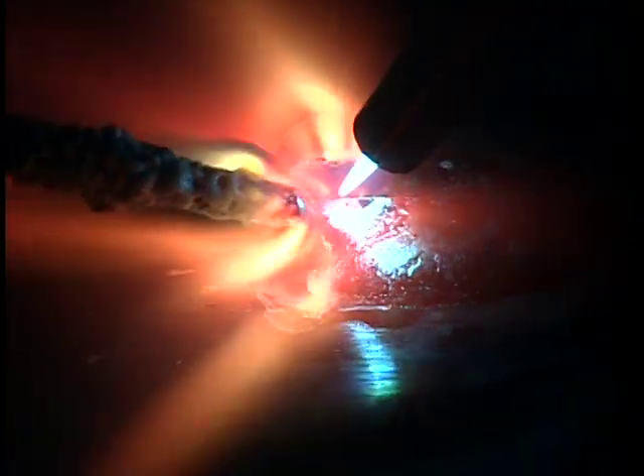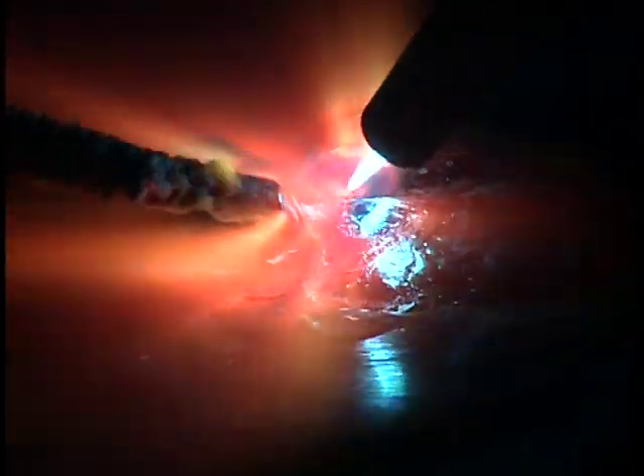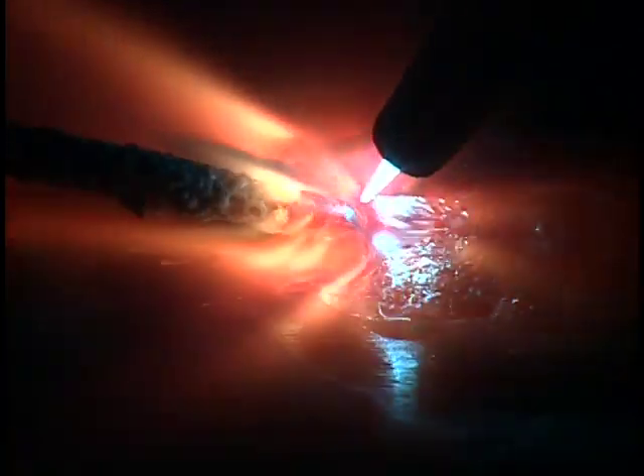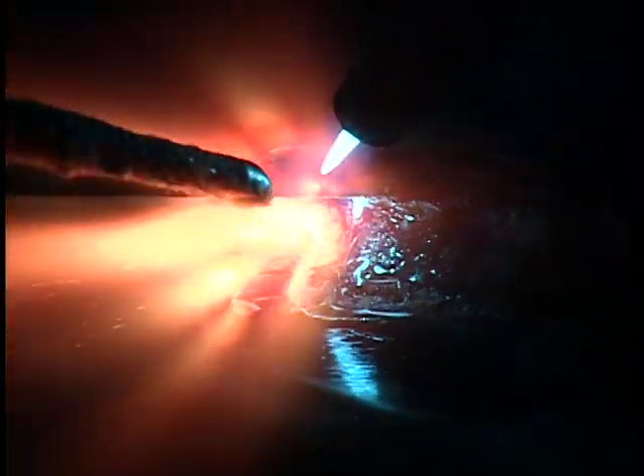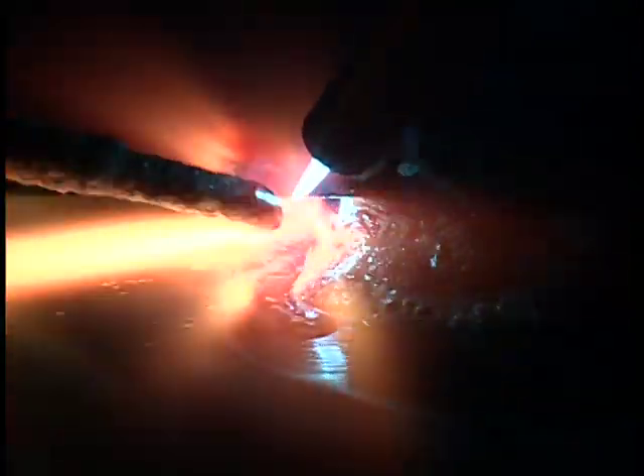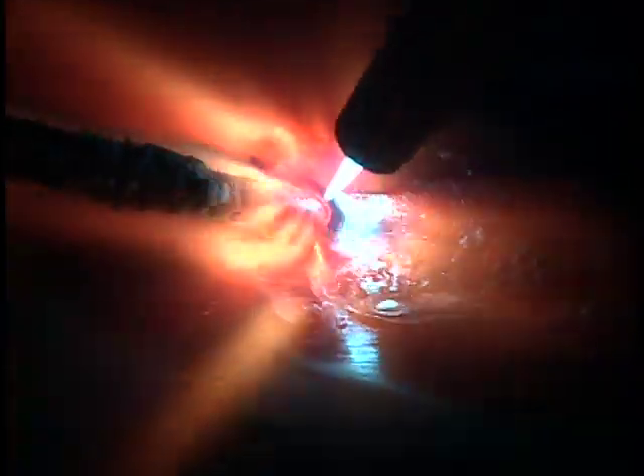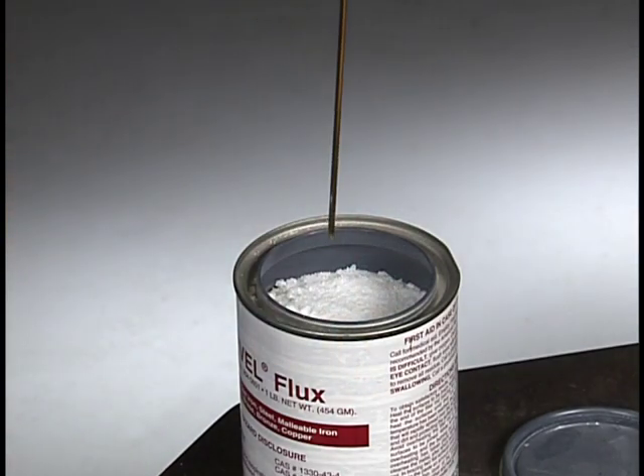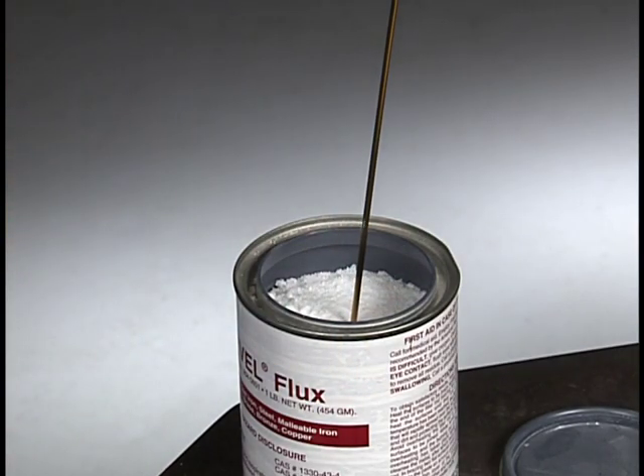Just heat the metal until it is hot enough to melt some of the flux when touched to the base metal. When the flux is liquid, dip the rod at the edge of the upper plate to deposit some filler metal. The filler should flow into the joint opening and wet out slightly. Continue dipping the rod and moving forward along the joint. Travel along the joint from right to left with a smooth and steady travel, adding filler metal as needed to fill the joint and produce the appropriate size fillet weld. Dip the rod in flux to replenish the supply when needed.